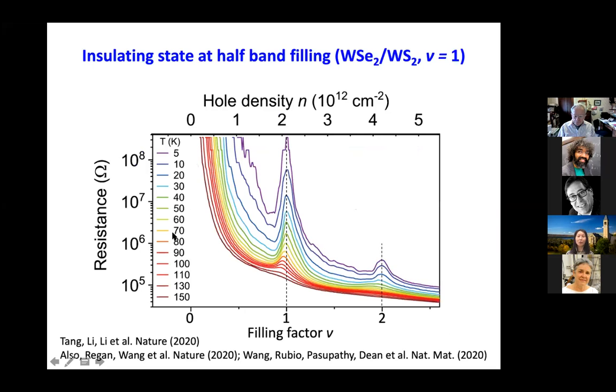First, let's look at the transport result. This is the resistance of the sample as a function of filling factor, how many electrons per Moiré site: 1 electron per Moiré site, 2 electrons per Moiré site, and as a function of temperature. You can see here that we have 2 very pronounced peaks at 1 particle per site and also 2 particles per site. The response at very low particle per site is a little bit artificial, because the contacts give you a large response. So let's just look at those 2 peaks.